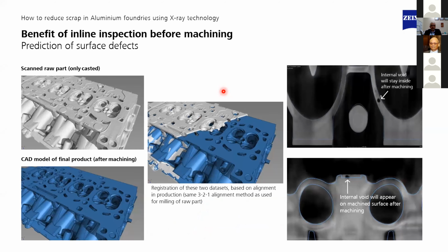So what we do is, normally, how the defects are identified. For example, this is the CAD image of the part, and then there's a raw scanned image. We superimpose the raw data with the scan data, and we do a 3-2-1 alignment method, just like how it is done in a production cycle. And then we see these defects. For example, we can make a judgment based on the position of these defects.